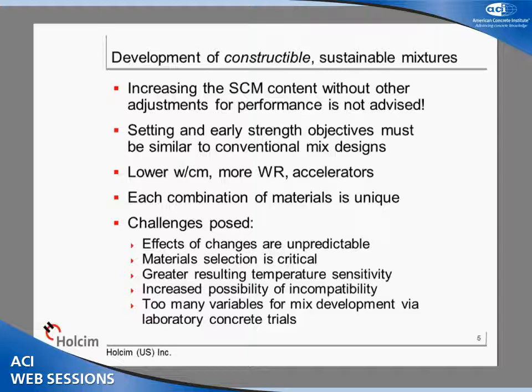So one thing that's been found to be problematic whenever we're mandated to go to a very high level of supplementary cementitious materials is if all you do is simply increase the replacement rate of your fly ash from 25 to 50%, you're probably going to have some performance problems on your hands. So this might be a protocol that might be of interest in the next few slides here in restoring acceptable performances. And these are the related challenges.